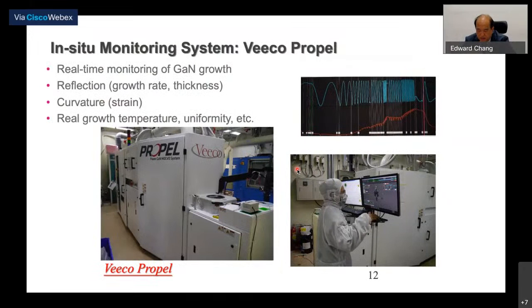To grow the material, because of the mismatch in the lattice constant, you need a lot of tools to monitor the activity during the growth. For example, you have to monitor the growth rate. You have to monitor the reflectance, which gives you the growth rate and thickness. And then you monitor the curvature, because this gives you the strain of the material. If the strain is too high, the material will crack or peel off. And then you need real growth temperature and uniformity. So this can all be done by laser sensors.